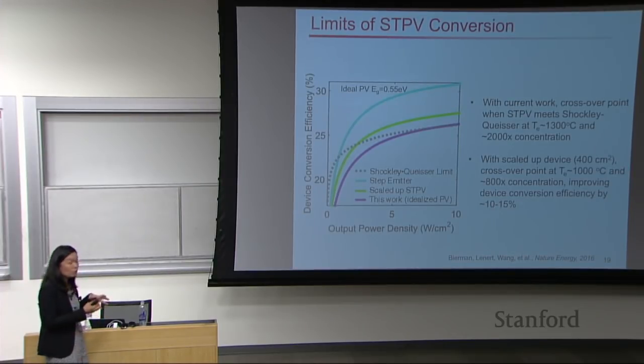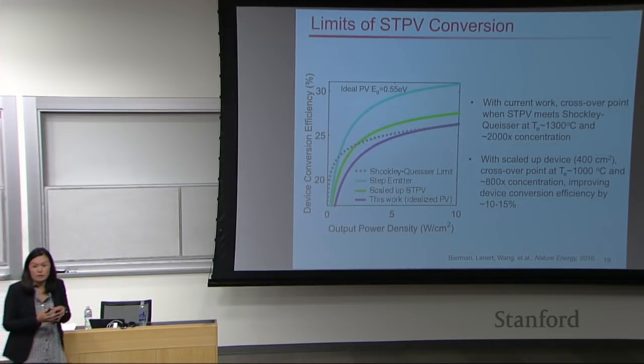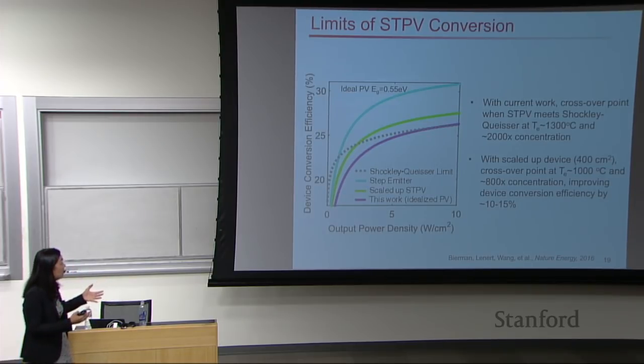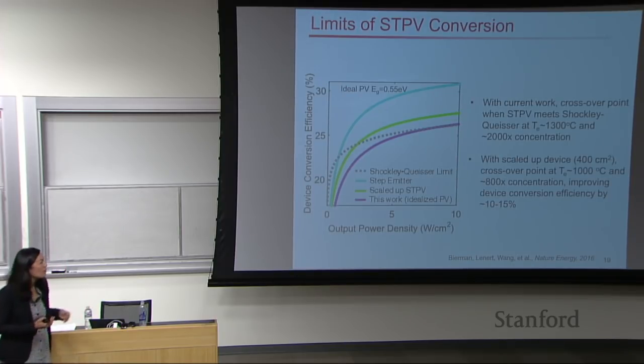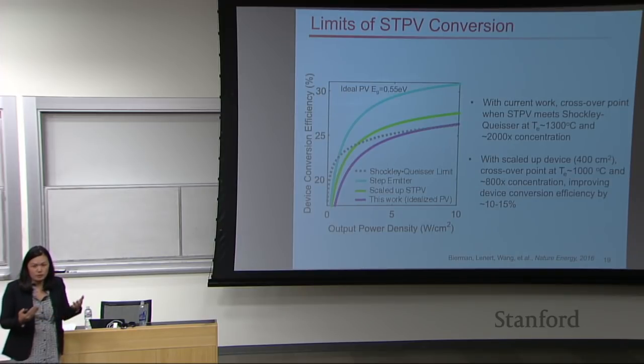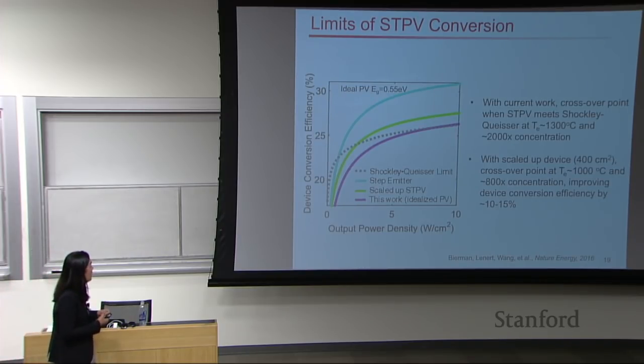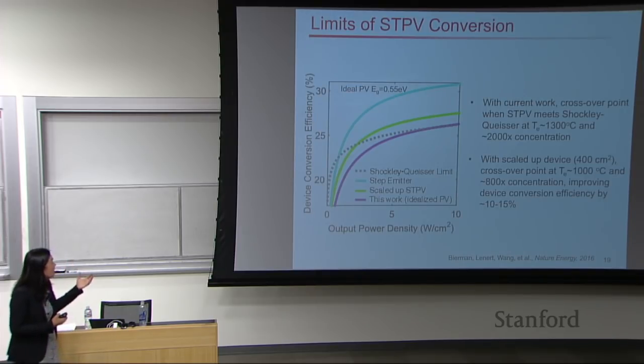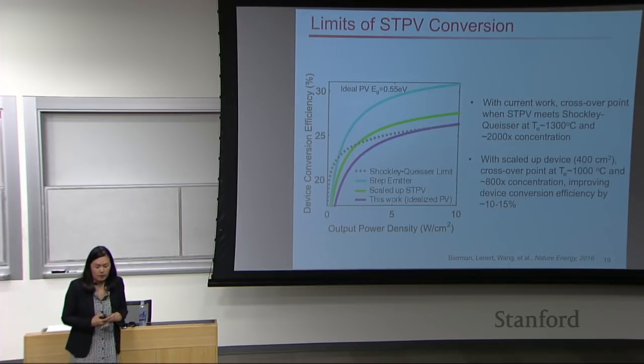But this is also still a relatively small device, and we envision a system such that we scale up, say about a 400 centimeter square device. We can see that the crossover point for this scaled up STPV device is in the green here. And the crossover is about 1,000 degrees Celsius for the emitter with about 800x concentration. So we're still at relatively reduced concentrations compared to what's been demonstrated before. And we can get to efficiencies such that they become competitive and we can think about this technology as deployable.